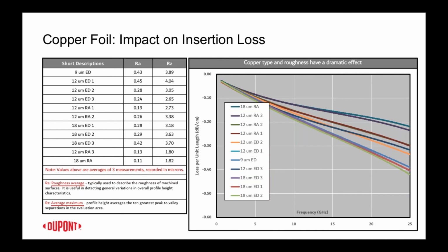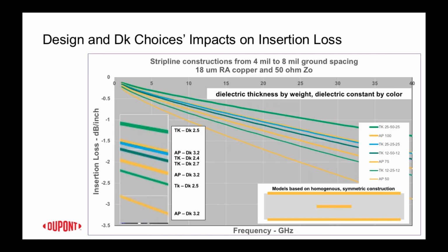A brief description of the foils' respective surface roughness values is shown on the left, and again, this data will be available. So here, this one's a representation of some modeling that we've conducted that varies dielectric thickness by weight, and for the picture, and dielectric constant by color. This is again a set of curves that runs up to 40 gigahertz. The inset on the left is how all the different varieties of laminate materials ranked. It's the same copper foil, and for each of these situations, it's a strip line construction of a 50 ohm characteristic impedance line.